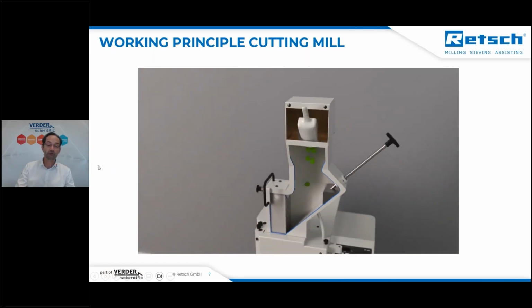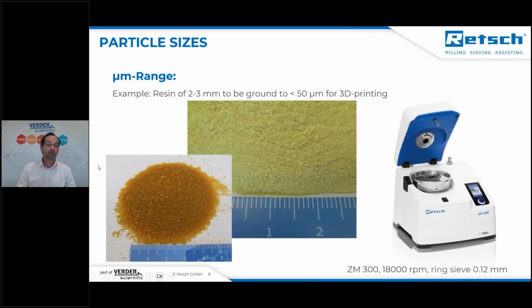So just switching to the next slide. Another application was grinding of resins down to a micrometer range. So this also is easily possible, but you need a special machine for that. In this case, it was a resin with the size of 2 to 3 millimeters. And that had to be ground down to less than 50 micron to allow a use for 3D printing. And we need this small size to avoid the clogging of the nozzles. And then we need a very fine powder.